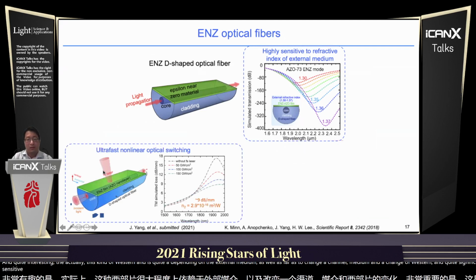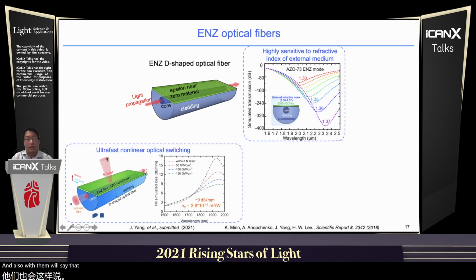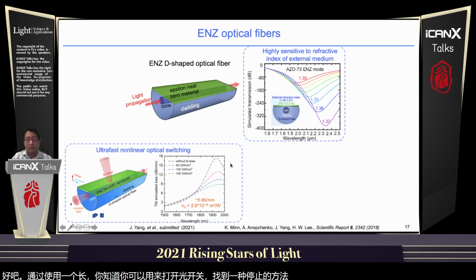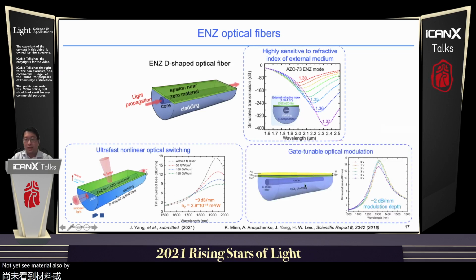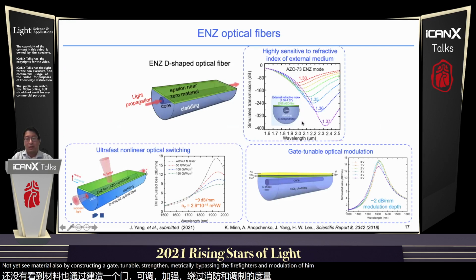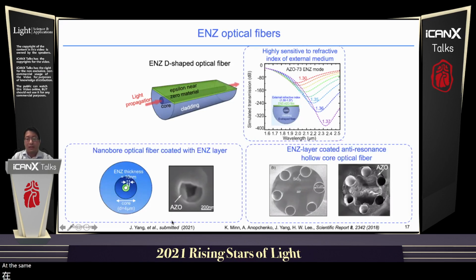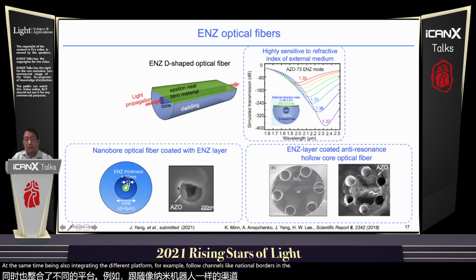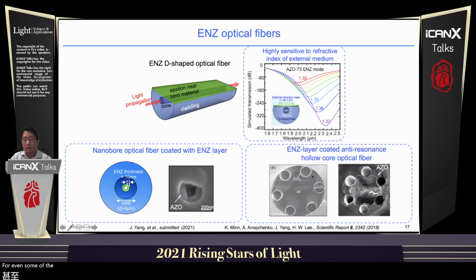We also demonstrate that by using the nonlinearity, you can realize optical switching on a fiber; we are able to demonstrate quite decent modulation using the nonlinearity of the ENZ material. Also, by constructing a gate-tunable structure, you can electrically bias it with quite decent modulation. At the same time, we are also integrating with different platforms, for example hollow channel nanobore fiber using ALD to coat the AZO inside the hollow fiber, or even the interesting anti-resonant hollow core fiber, where we can coat some material as well.